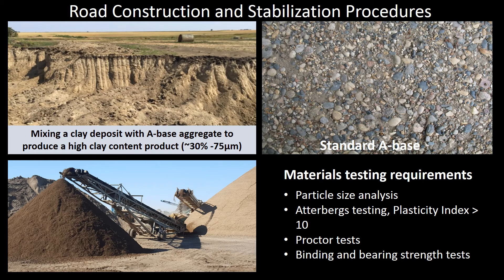To understand the role of cohesive clays, we can walk through the construction and stabilization process. Step one is to take standard A base with a good particle size distribution and combine it with a high-plasticity-index clay deposit. The material can be blended in a quarry. This requires testing, including particle size analysis to determine the correct blend. Atterberg testing is carried out to ensure that the clay deposit has a high plasticity index and that the plasticity index of the final blend is 10 or more. Proctor tests are carried out on the final blend to determine optimum moisture content, and binding and bearing strength tests are also performed. The blended material must produce a compacted six- to eight-inch wearing course on the road being stabilized.